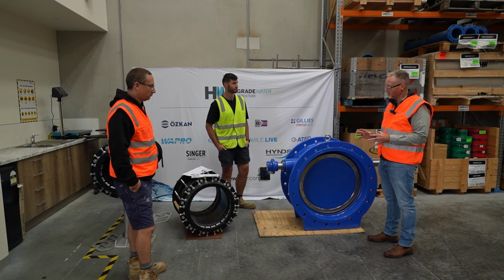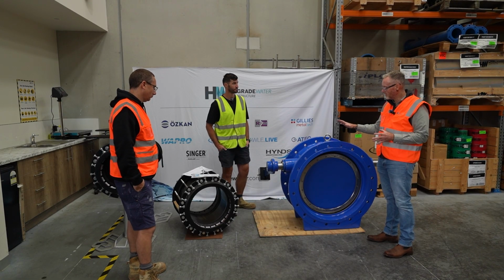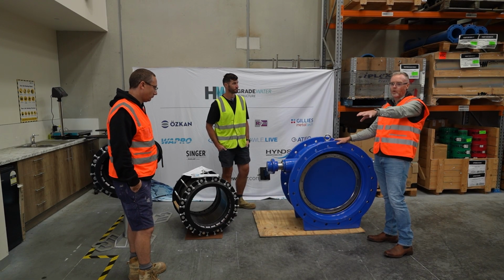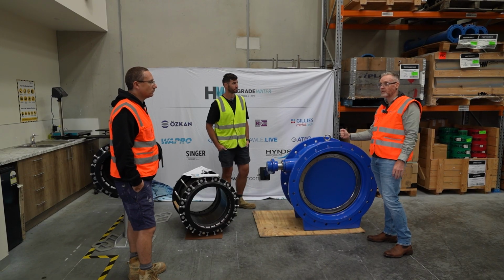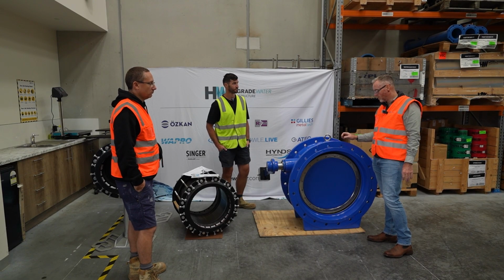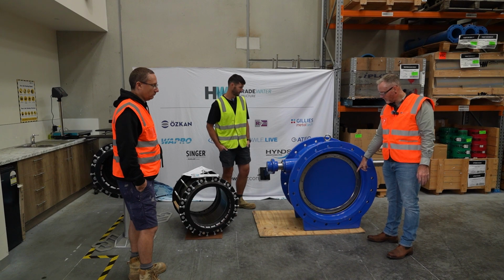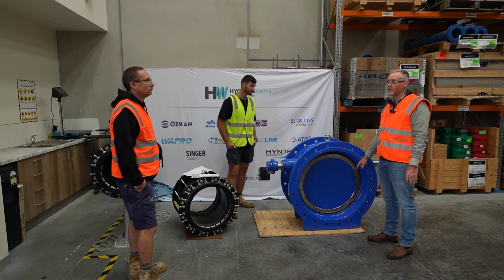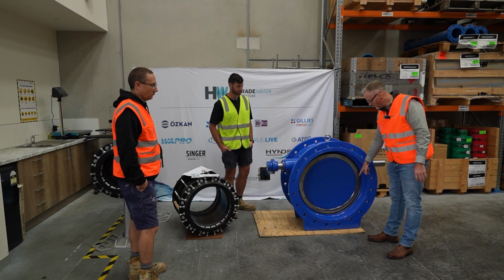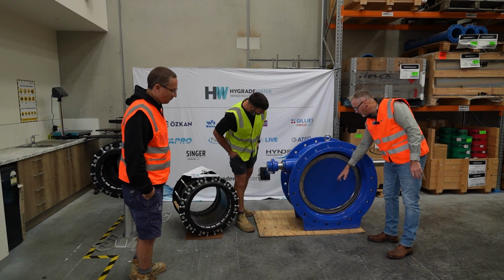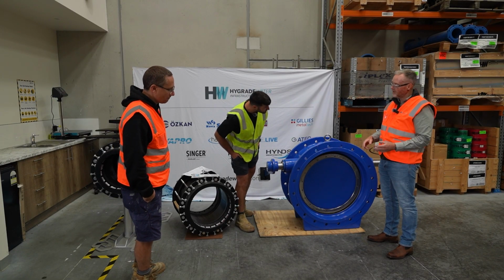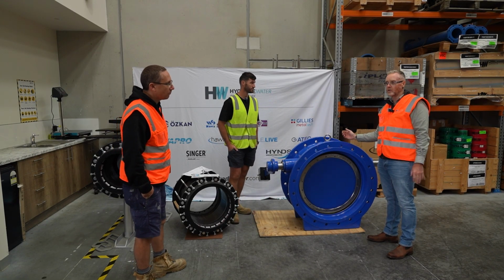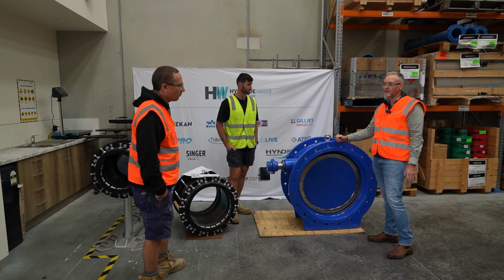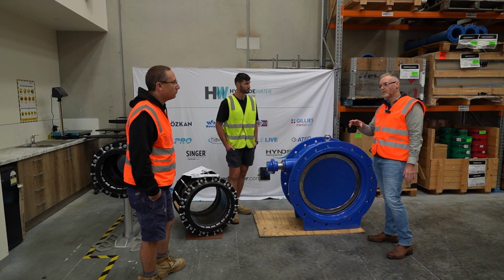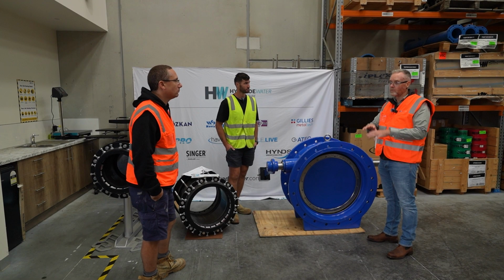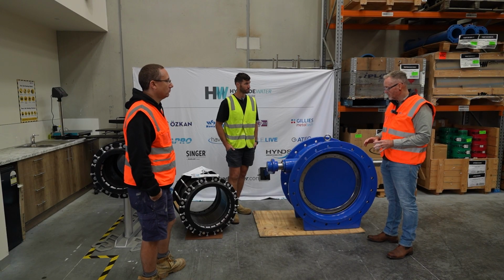Why that's important, and why the material, as we talked about before with those valves around the 400 material, is that we're one of a few that can weld a stainless steel seat to our valve. So in this one here, you can see there's a stainless steel seat on the inside. Because of the material, you can actually weld stainless steel to ductile iron. We have robotic welders that weld that to the seat.